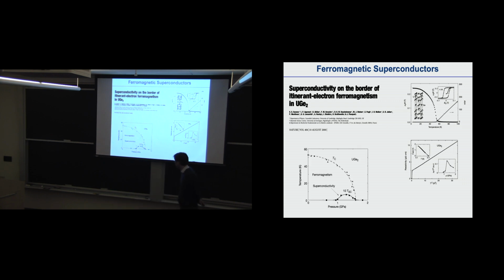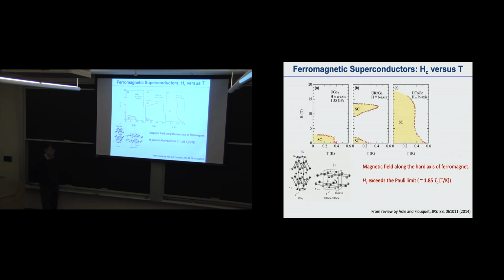This was done under pressure, and by controlling pressure you can kill both the superconductivity and ferromagnetism at the same pressure. This strongly indicates there might be some interesting tie between ferromagnetism and superconductivity. After this, the community found a few other compounds, mostly uranium-containing heavy fermion systems, and some of them become superconducting and ferromagnetic even without pressure, at ambient pressure, right?